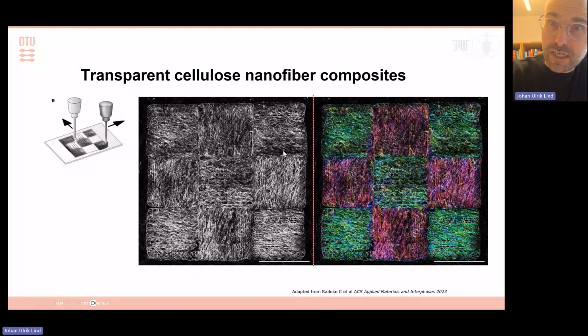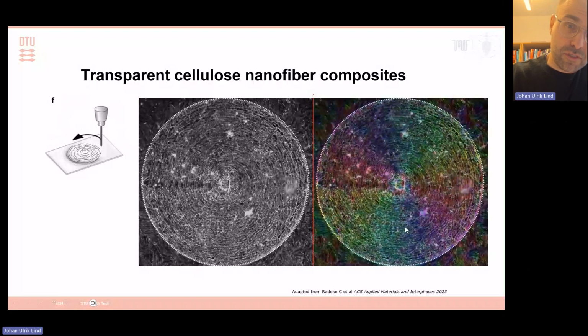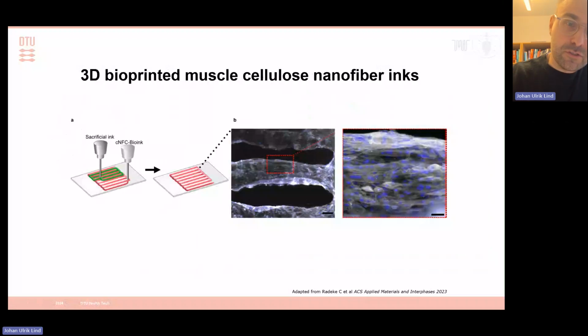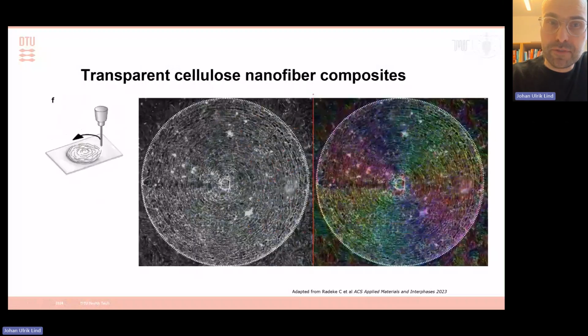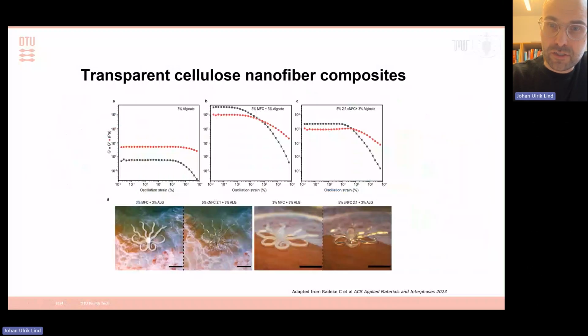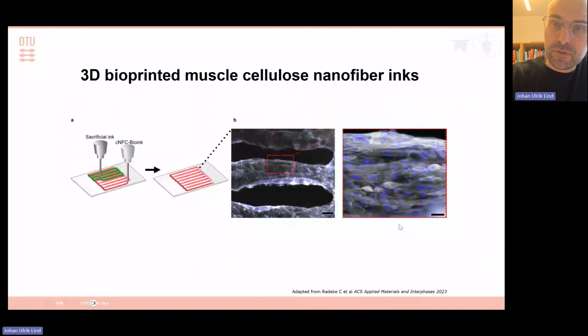So if we print them in a checkerboard, we will get orthogonal orientation in the checkerboard areas. And if we print a circle, now we get circular patterns and not spiraling patterns. So now we are using this for different applications. I'm going to show a few later in the presentation. But obviously, you can use the same fibers also in traditional bioprinting. But there are some limitations for how high concentrations you can go here without getting into shears that will damage the cells.